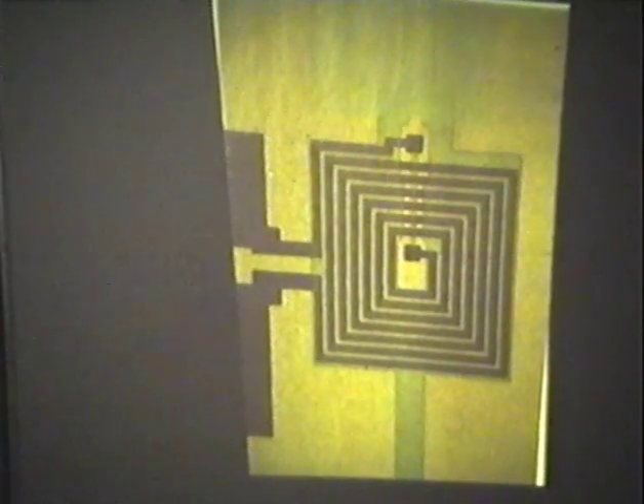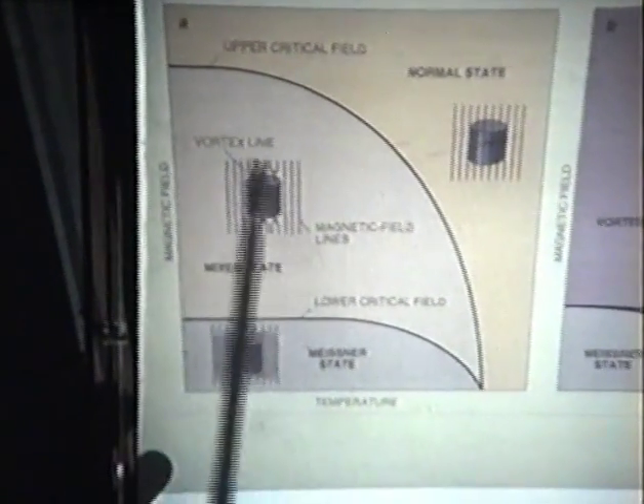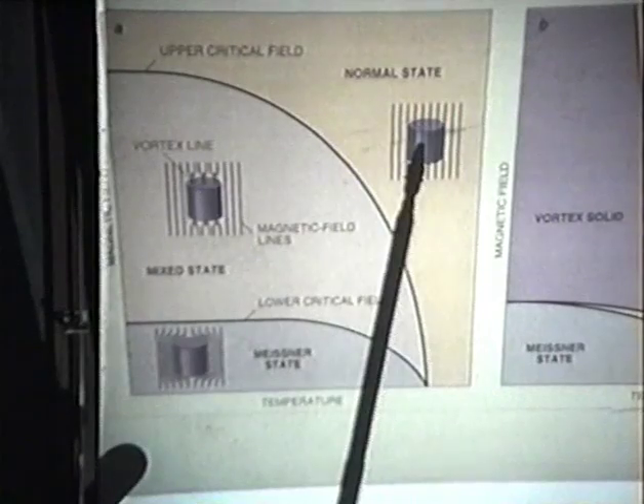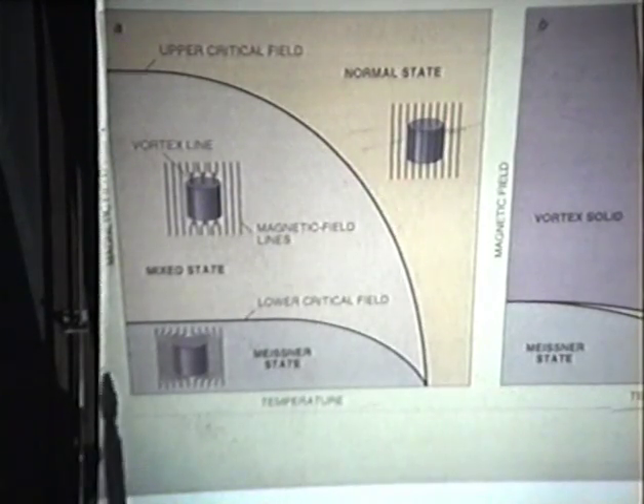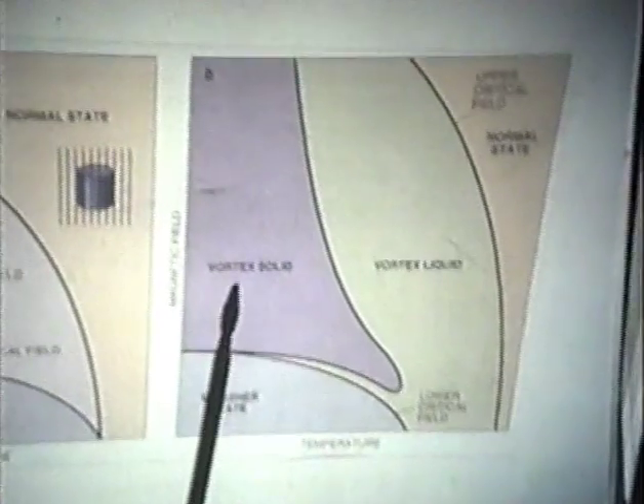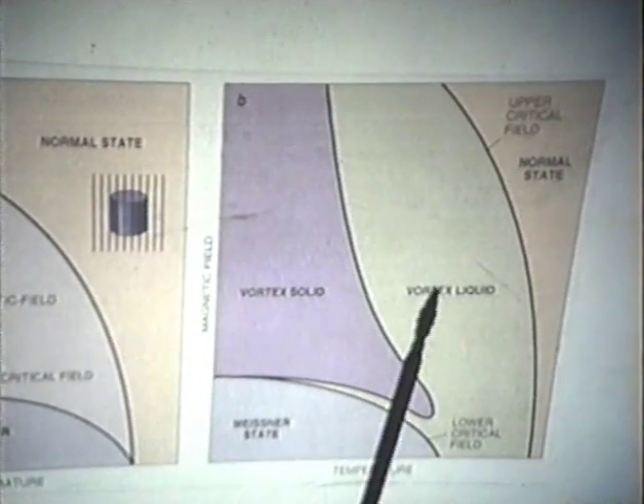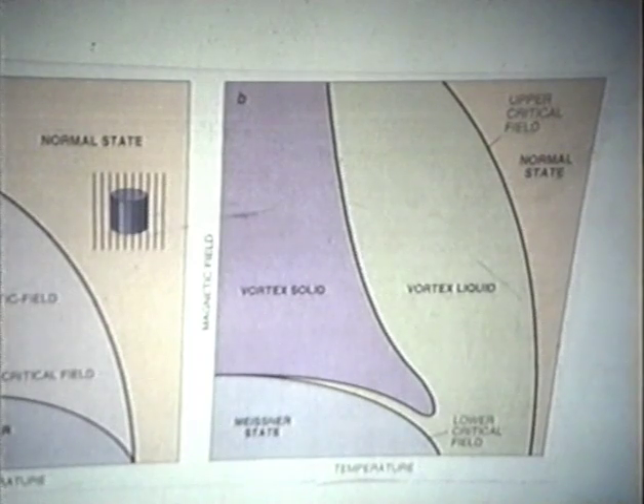Okay, so it's time now to see what these new superconductors can do and what sort of applications they can have. Well, the new superconductors turn out to behave a bit like the old superconductors. Here are the old superconductors with the pure superconducting state. Here's the vortex state where the vortex line, the field begins to penetrate through the material, and then finally here's the normal state as you raise the temperature or raise the magnetic field. Well, the new superconductors are a little bit more complicated. They also go through this vortex state, but they have this new state here called the vortex liquid.